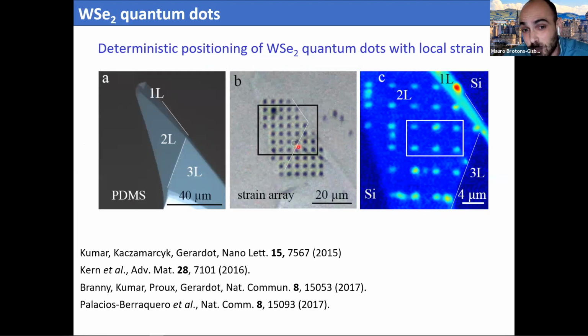In tungsten selenide, it's possible to use strain to have deterministic positioning of the quantum dots. Okay, so I wanted to show you here a few works where basically what the people did was to take one of these layers and transfer it on top of an array of nanocolumns, and the strain generated by the nanocolumns basically, as you can see here, gives rise to an array of quantum dots in photoluminescence.